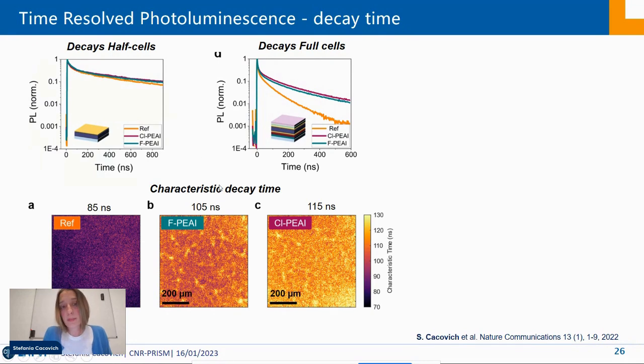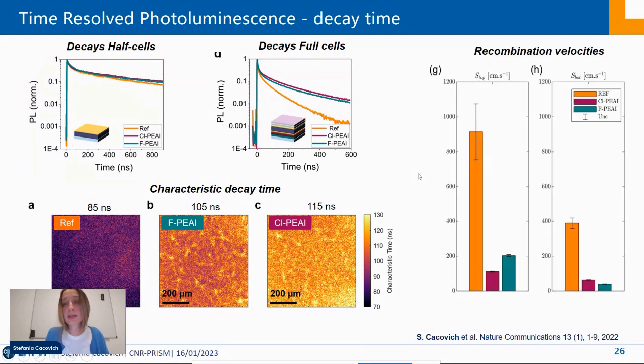And these are the maps of the decay time. So we can note that the decay time has improved all over the thin films. And we also calculate the surface recombination velocities at top and at the bottom, and we can see that there is an evident reduction in terms of recombination velocities.